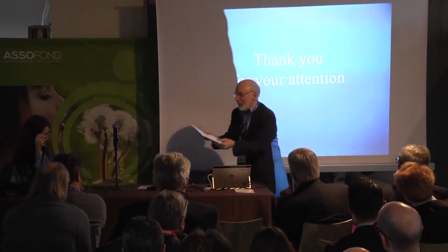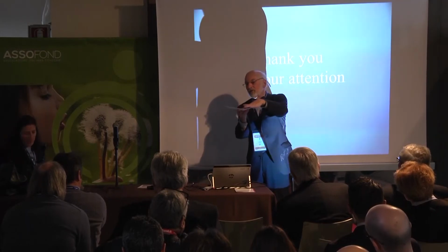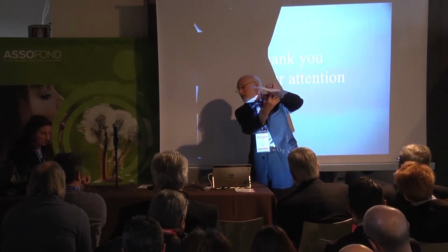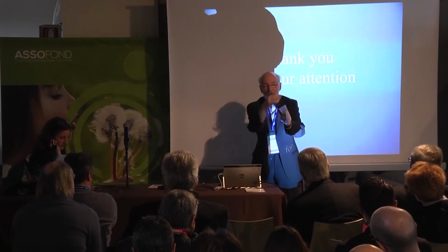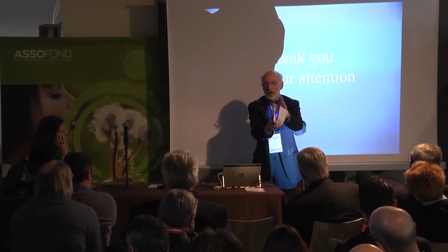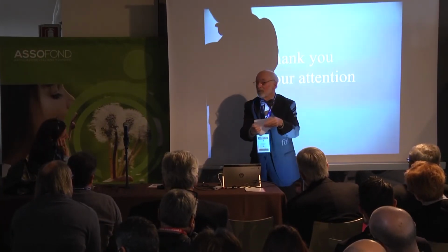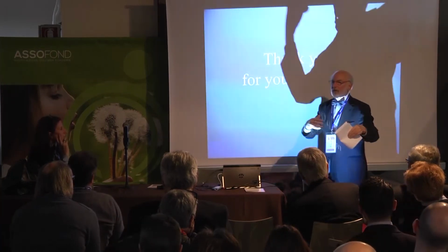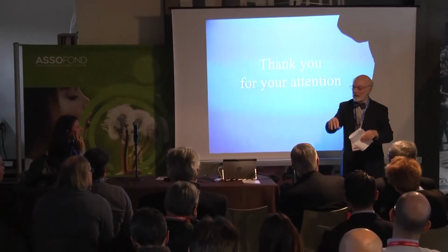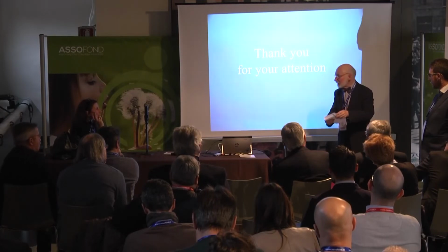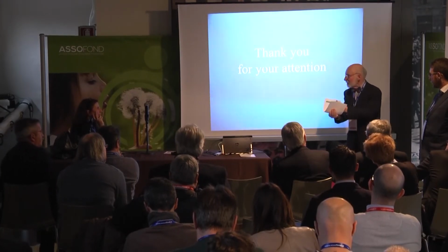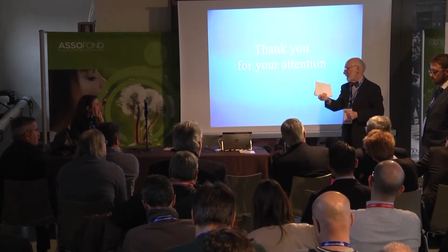You remember, the inside and the top surface is dry, the bottom surface is in atomic contact. Now the bifilm has surfaces in atomic contact, but is cracked down the middle. And so when steel people talk about brittle carbides at the grain boundaries, this is rubbish. The carbides are ductile. They appear to be cracked because they've got a bifilm down the middle.